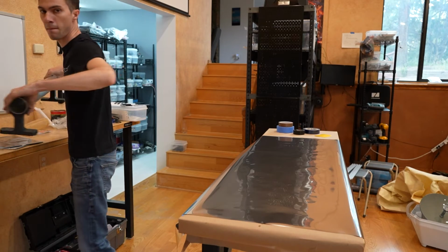System Three resin is awesome because it has a high service temperature, so I can use it for high-speed rocket flight without worrying about it softening under the high temperatures. The System Three resin does require a post-cure though, so there's a little more work to do after I make the tube than if I used a room temperature cure resin system. Now the trick to doing composites is always to do the preparation before you mix any epoxy.